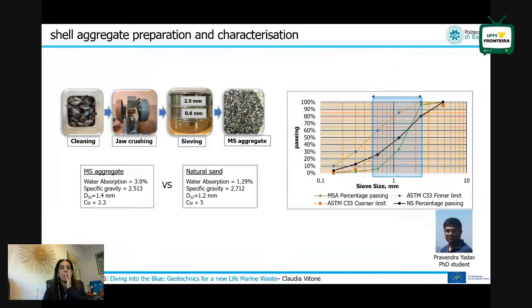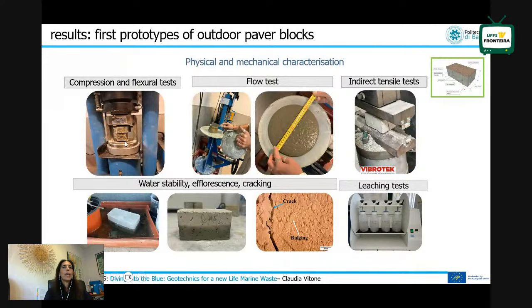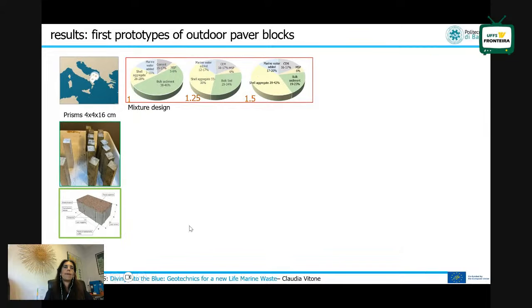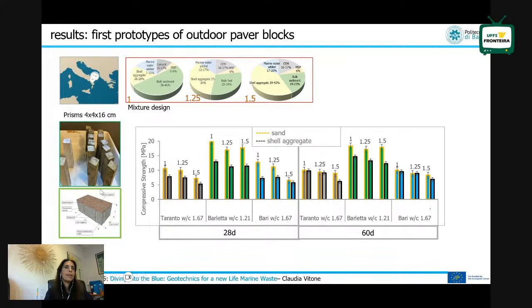This is part of the work of Pravendra, our PhD student, who is working with these products. As you can see here, we have compared the mussel shell aggregate performance with that of the natural sand. We had to also calibrate the grain size distribution. We have characterized the chemomechanical performance of the bricks of the new pavements, and this is just one result from Pravendra. Now there is also Hossein Sadiki, who is now starting on this.